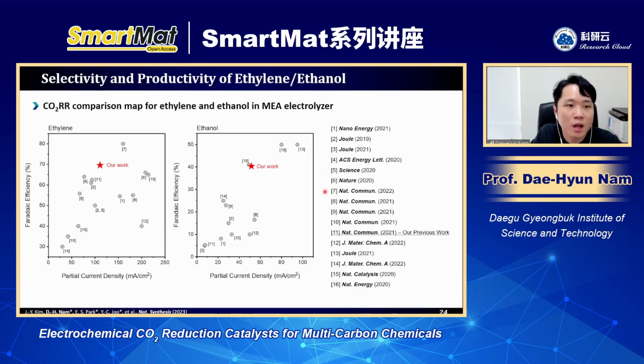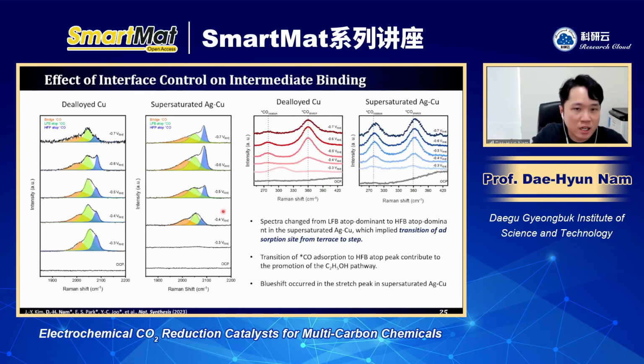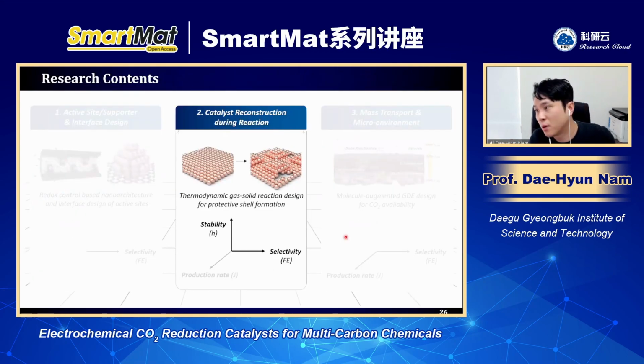And to understand why these catalysts are effective for controlling the ethylene and ethanol selectivity, we did some in situ Raman study. And we found, in the case of the supersaturated silver-copper one, some adsorption site transition from terrace to the step site. And we found these are very effective to enhance ethanol production. So this is how we designed the catalyst surface to control the selectivity. And now I'm going to move on to the second part, to understand the reconstruction of the catalyst.